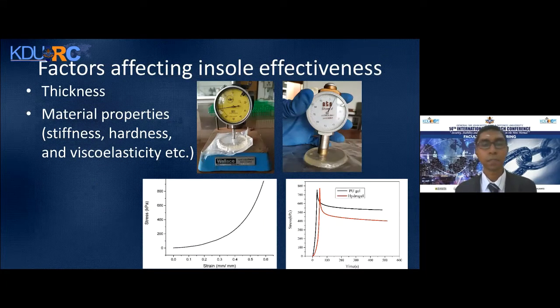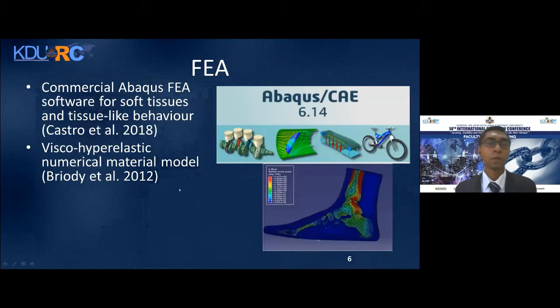First, starting with the experimental and laboratory practices used in this research, we measured the thickness using a thickness gauge and measured the hardness. All the material properties were tested using a universal testing machine, including the stress-strain behavior and stiffness, and also a stress relaxation test to acquire the viscoelastic properties. For the finite element analysis part, the commercial Abaqus finite element analysis software was used, and the hydrogel was modeled as a visco-hyperelastic material.